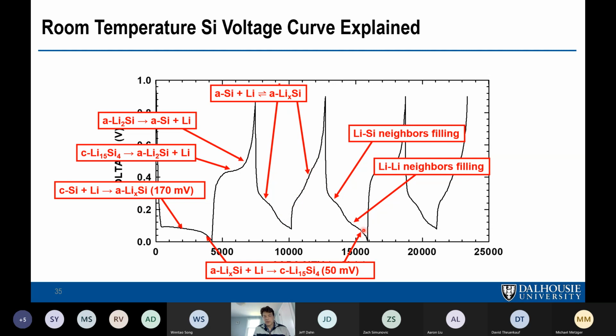If you go below 50 millivolts, the 15-4 phase will form, and the plateau, which I covered up again here with this label, shows up again. And so this explains this history-dependent voltage curve of silicon, which I think is pretty unique among lithium battery materials. I really don't know anything like it.